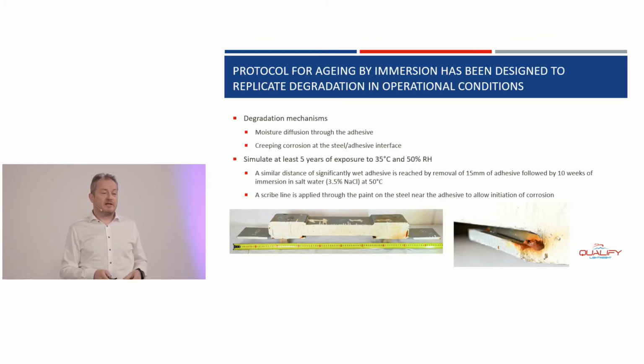That aging protocol has been designed based on full immersion in salt water at higher temperatures. Linda already initiated in her presentation some background on the calculations that were performed. The ambition of this protocol is to mimic the same types of degradation mechanisms: on one hand, moisture uptake and diffusion throughout the adhesive, and on the other hand, potential creeping corrosion at the interface between adhesive and steel. Those were the two degradation mechanisms that we were aiming at.